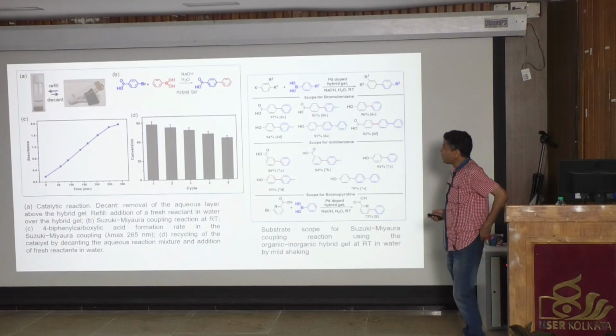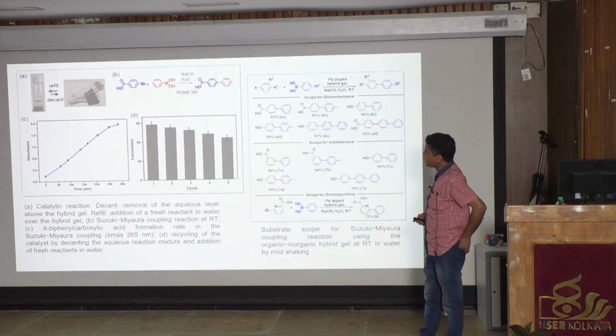And now, how to utilize it. So this is the gel. On top of the gel, we add the aqueous mixture of phenylboronic acid and bromobenzoic acid in a little bit of sodium hydroxide. That is our reaction medium on top of the gel, and the palladium is actually in the gel. We let it sit for 5 hours, and the boronic acid and bromobenzoic acid will react and form the compound. Once the compound forms, we just decant the aqueous layer and acidify it, we get back the product, and we separate the product by filtration.